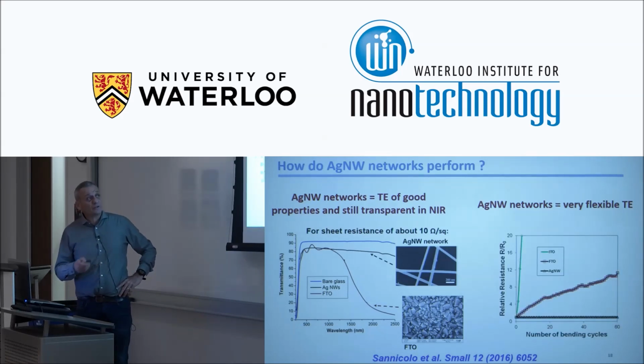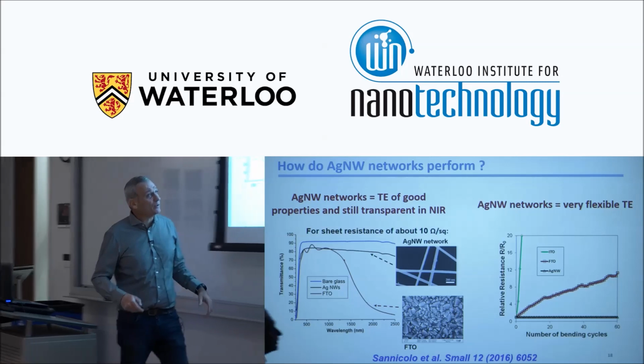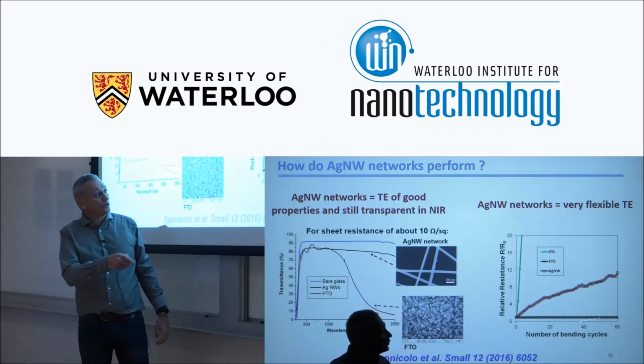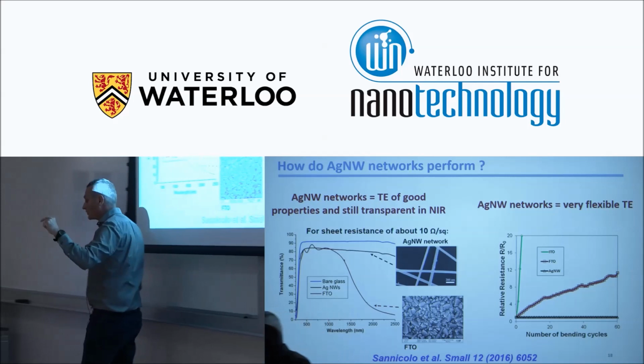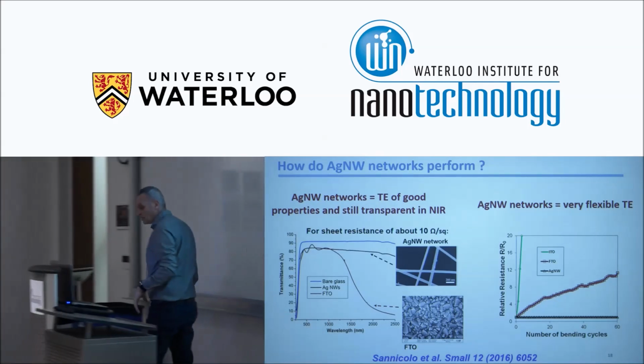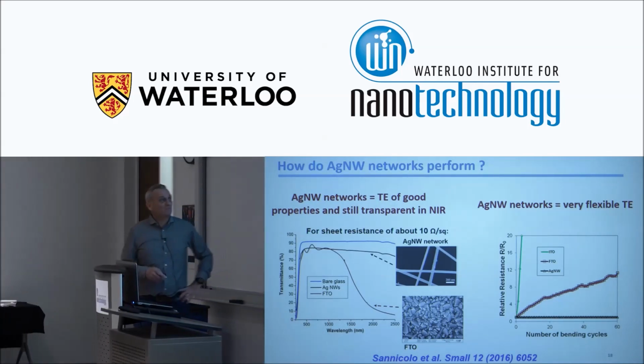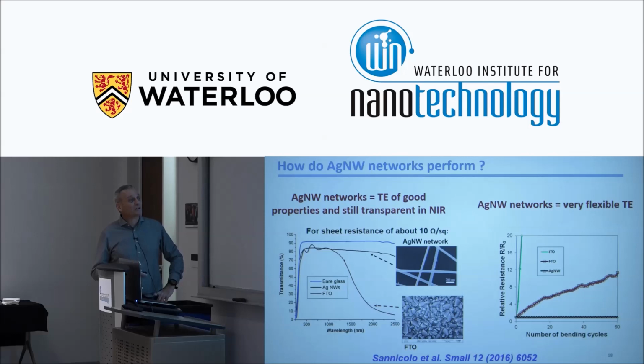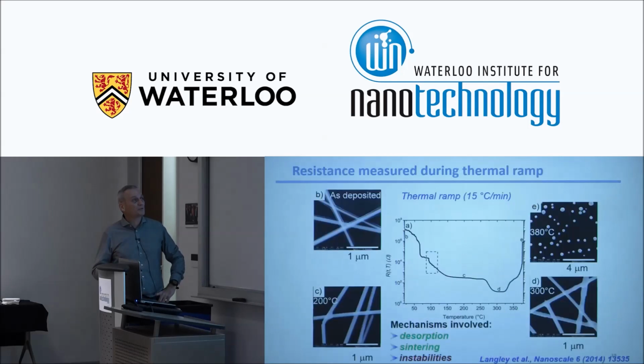We measure here the electrical resistance after bending cycles with a radius of curvature of 5 millimeters. And for ITO, for example, after only 1, 2, 3 cycles, we have multiplied the resistance by a factor of 20. It's much better with FTO, but it's so flexible for silver nanowires. We can do that thousands of times. There is no problem. It's very, very flexible. That's the main two assets of silver nanowire networks compared to other materials like TCO, for example.